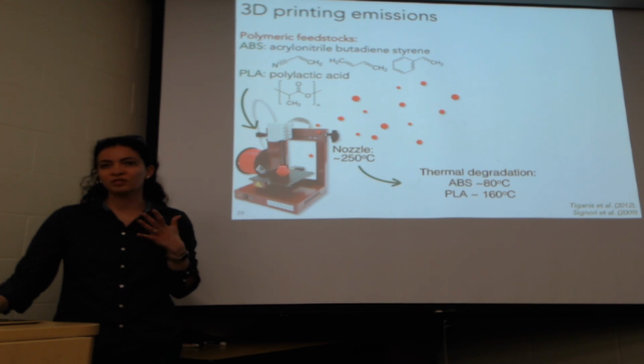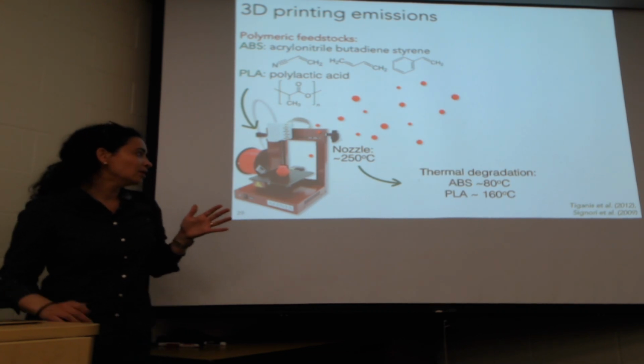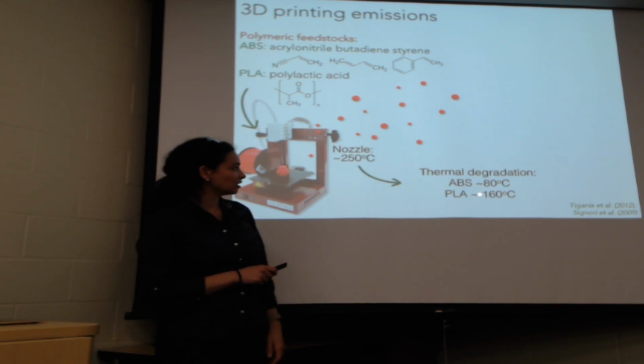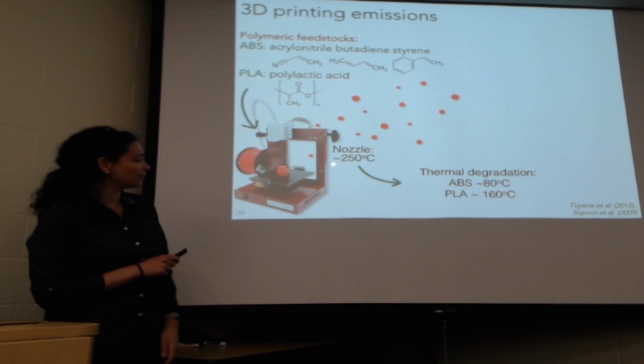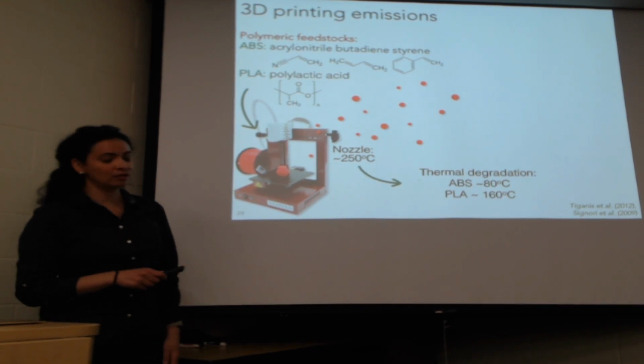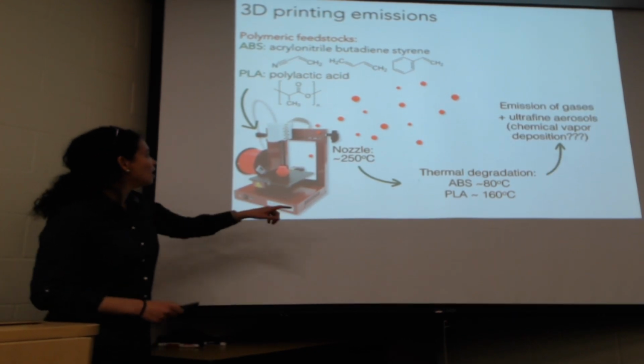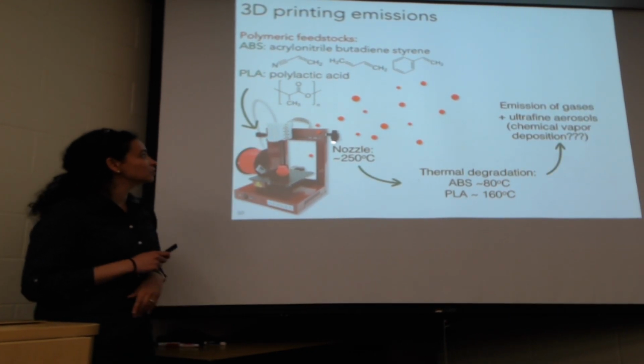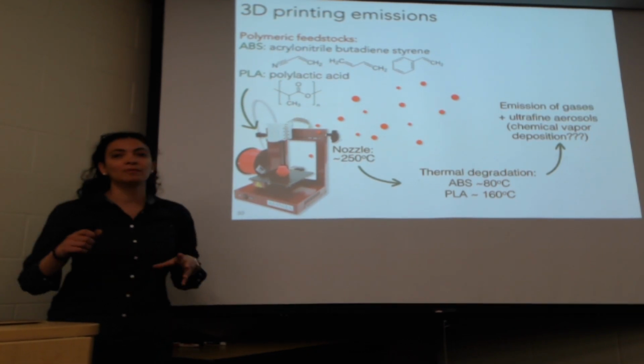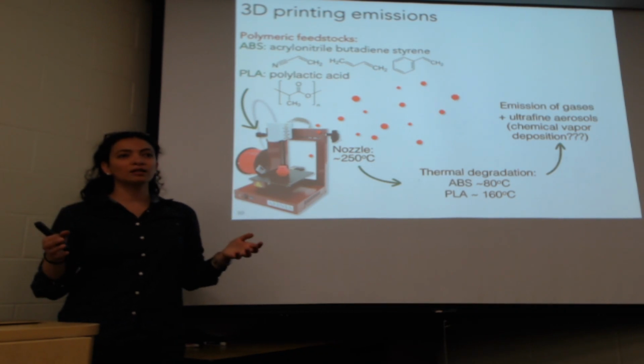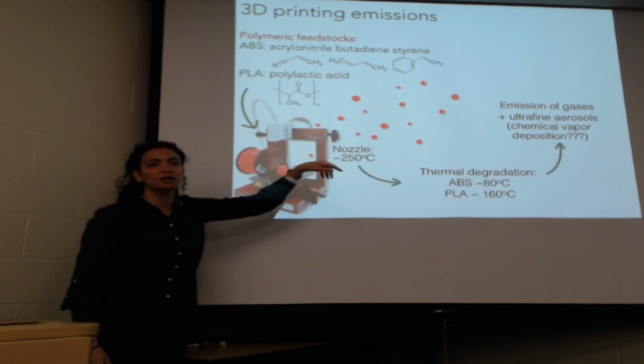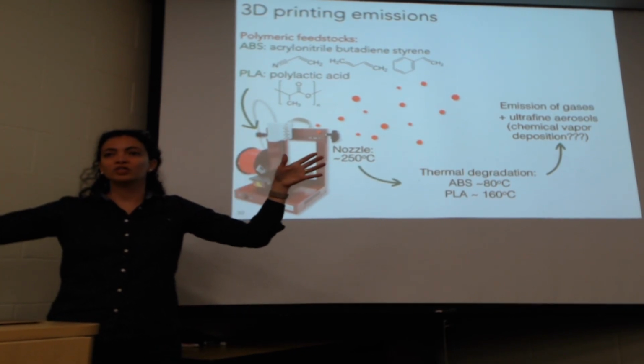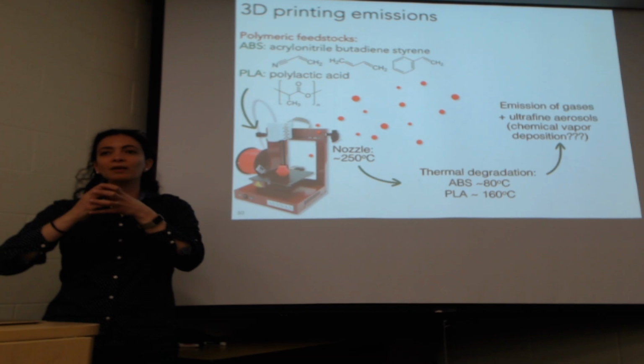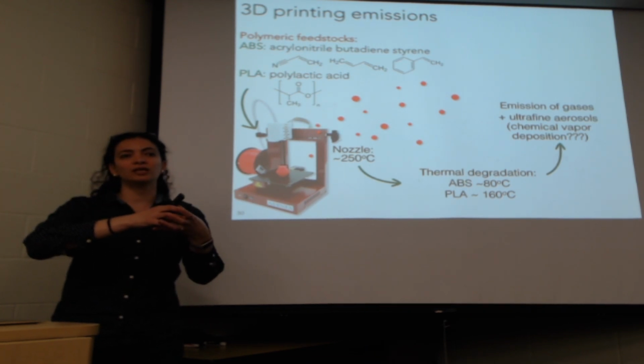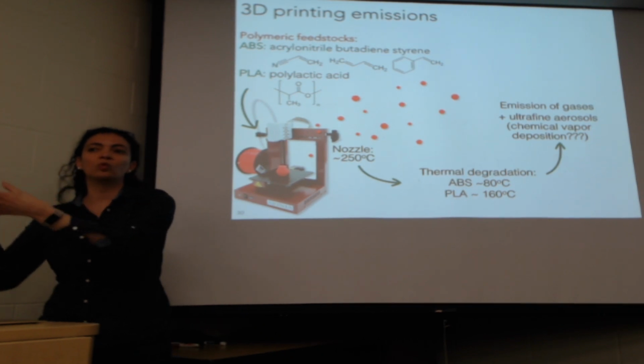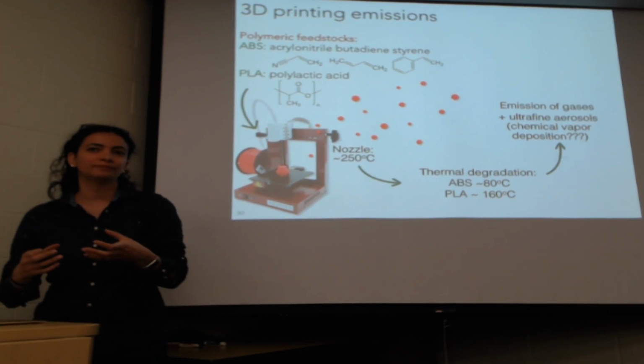And what we found, from some theoretical search in the literature, was that the thermal degradation of these materials starts before you reach the temperature of the nozzle. So there's definitely a possibility for these materials to be degrading as they're touching the heated nozzle, and to then break up into either their monomers or maybe some smaller molecules that are small enough to be volatile at this region, at this temperature. But once they leave that area and they reach room temperature, then they recondense back. Because these molecules might be small enough to be volatile at 250, but not at 21 Celsius, which is the room temperature. Does that make sense? Cool.